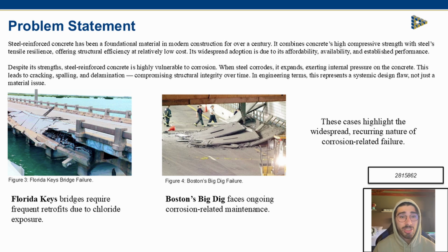That expansion exerts internal stresses on the surrounding concrete, leading to cracking, spalling, and ultimately structural failure. In engineering terms, it's not just a material flaw, it's a systematic design vulnerability. This isn't a theoretical concern. We've seen it in the Florida Keys and in Boston's Big Dig. These failures are not isolated, they're endemic, and the cost isn't just financial. Every crack is a compromise, every repair is a risk, every failure is a warning.